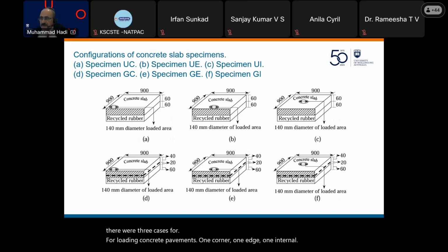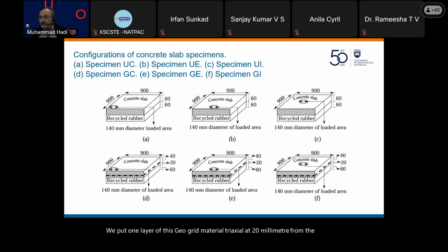In this part of the research, we did 6 specimens, 3 unreinforced, 3 reinforced. And we tested them under loading of the concrete slab, loaded at the corner, edge, and internal. The slabs were 900 by 900 millimeters, and the depth 60 millimeters. We put one layer of this geogrid material, triaxial, at 20 millimeters from the bottom of the slab. The load was circular, 140 millimeter diameter. So all those were easy.